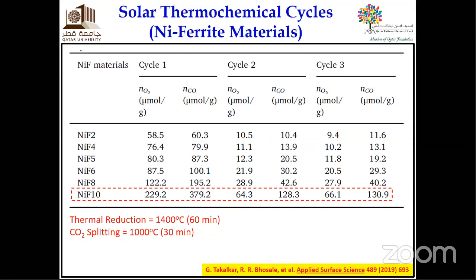As I told you, we have 6 different nickel ferrites synthesized. Here we did 3 cycles, cycle 1, cycle 2, cycle 3. And if you compare the ferrites together, the last one, NIF10, seems to be the most beneficial ferrite in terms of fuel production capacity. It has the highest O2 release and the highest CO production at these conditions: thermal reduction at 1400 degrees Celsius for 60 minutes and CO2 splitting at 1000 degrees Celsius for 30 minutes.